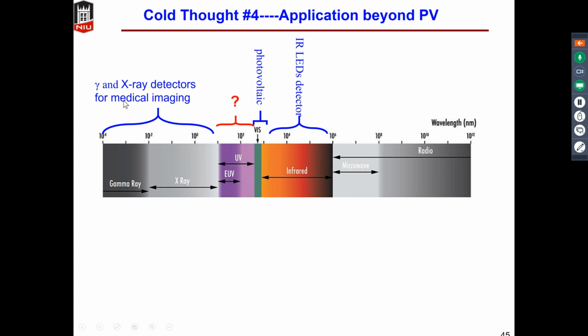using perovskite materials as gamma ray and X-ray detectors for medical imaging, because this lead-based perovskite is very sensitive to gamma ray and X-ray, and it can generate gamma ray or X-ray induced photoelectrons, which give you much better imaging resolution, because people can synthesize very tiny perovskite crystals.